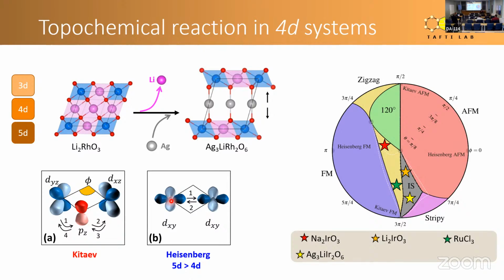And as such, although both K and J go down when you go from 5D to 4D, the Heisenberg interaction goes down faster. And therefore, the ratio of Kitaev to Heisenberg interaction actually increases. And it seems like the 4D transition metal honeycomb systems are a good place to look for Kitaev spin liquid. For example, ruthenium chloride is also a very well-known material that has been studied extensively in relation to Kitaev physics, and that is also a 4D transition metal.